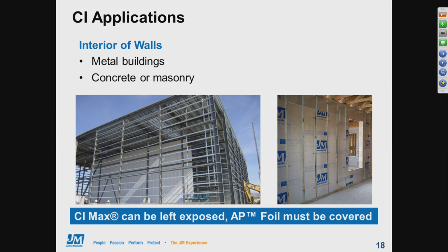So in an application like this, where we have a warehouse, where inside this warehouse we have a cold storage room, CI on the interior is a great solution, and CI Max in particular is a good solution because it can be left exposed. In this case, in the photo, a matching tape is all that we really need to create a well-sealed and insulated assembly. And of course, we can see in the photo, they've put a white tape on the face of this plain white board, so you get a pretty good clean look overall.